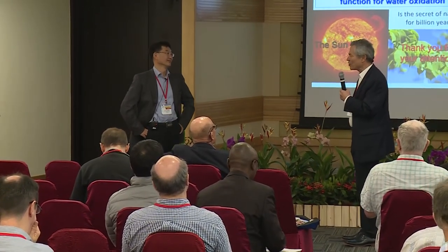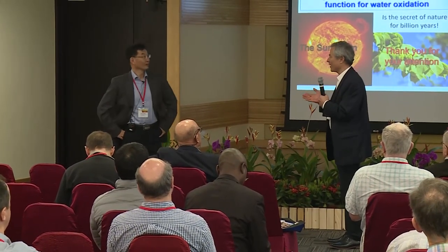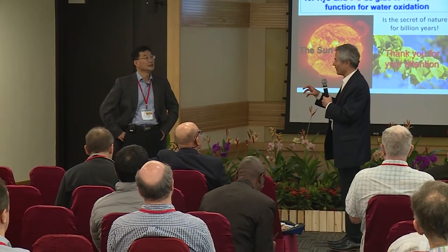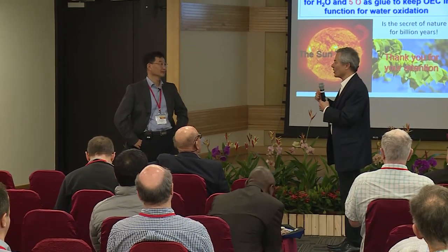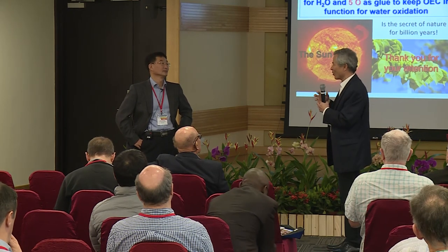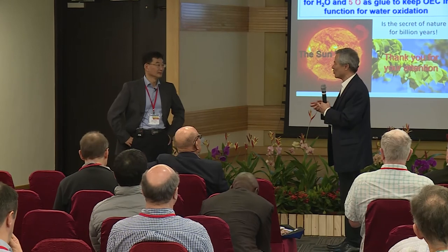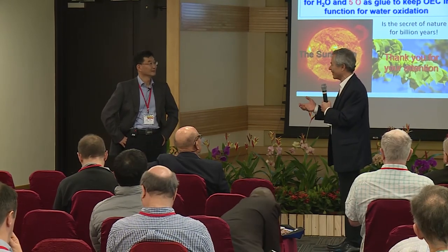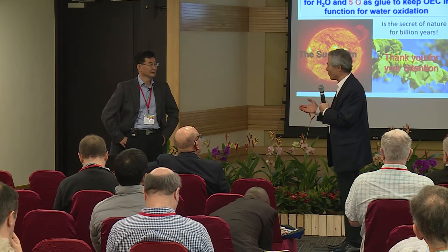And that sort of leads me to wonder why this would be active for a catalyst and not deactivate. So if you're in the S3 state, you're ready to disproportionate. And why? One of the things that leads to reactivity is formation of strong bonds. So permanganate is so kinetically inert because you've got four very strongly bonded oxos, and you're all set up to do that there. And so why don't you see permanganate formation in the S3 state?